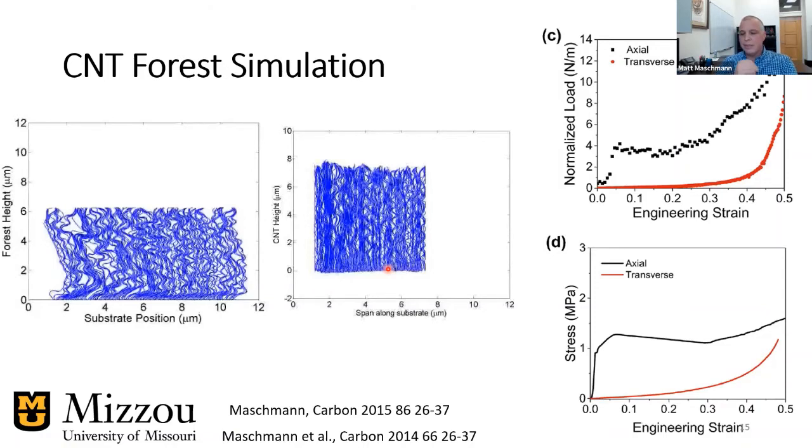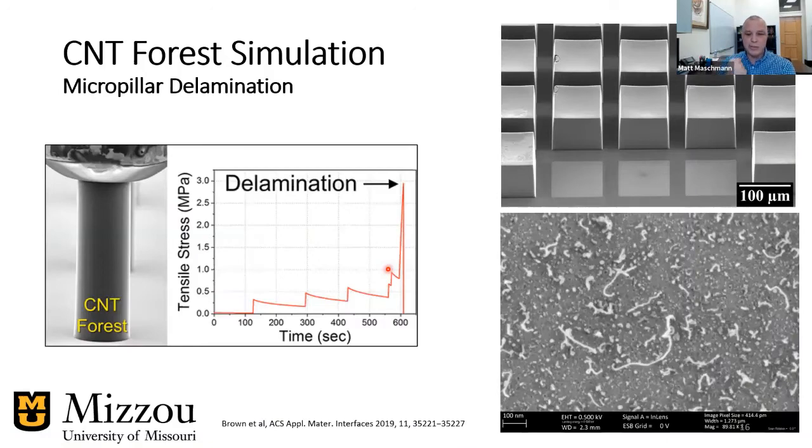And it's worth noting, I think, that all of the inputs that we were feeding to these simulations are extraordinarily simple. So we'd have like a Gaussian profile of the growth rate. So we'd input an average growth rate. All of the nanotubes you're seeing here are simulated as having the same diameter, which physically isn't true. But we can also grow them with whatever population that we want, honestly. But these results were all like the simplest possible things that we could throw at the simulation, and it was giving us some pretty good results.